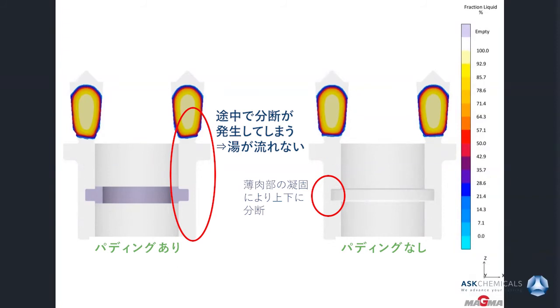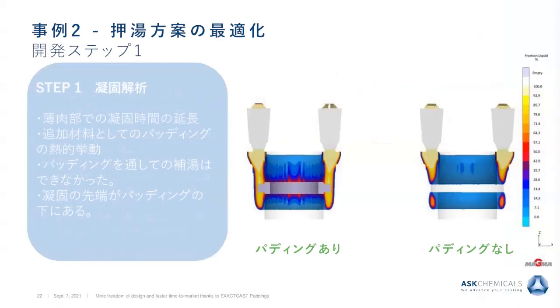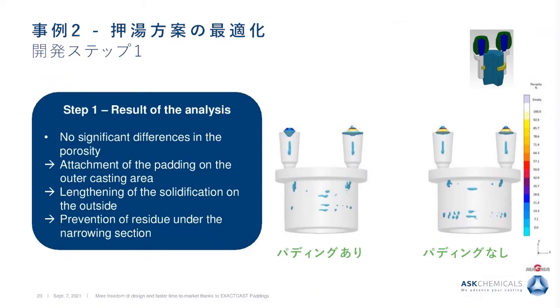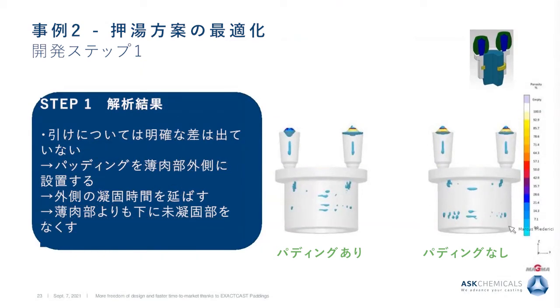However, there is a key limitation: the padding only works in the thermal way — there is no material transport through the padding. The padding is not steel, iron, or any metal, so a section within it remains unconnected to the rest of the solidification even if thermally it looks good. We also see a porosity issue at the narrowing section compared to the version without the padding, so we need to find another solution.